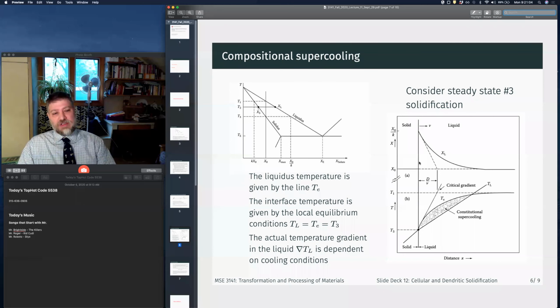So we've got this layer where solute is piled up, and at the interface we always have local equilibrium. When our solute concentration is X naught over K, the solid is always solidifying at X naught, which is our alloy composition. But out in front, far away, the liquid is actually at the alloy composition X naught. And we can see that the freezing temperature at the interface is cooler than the freezing temperature of the liquid way out here.